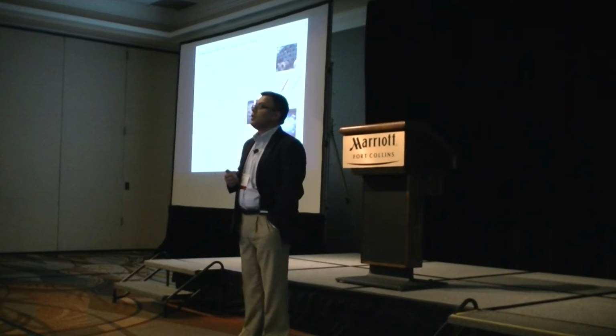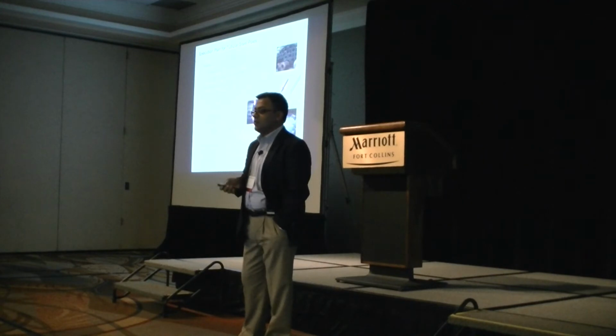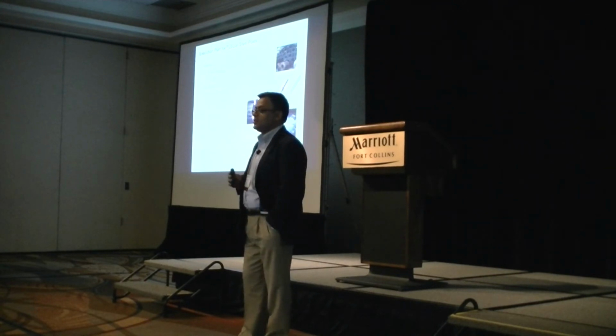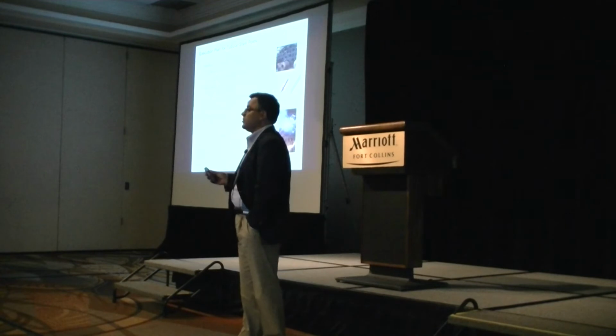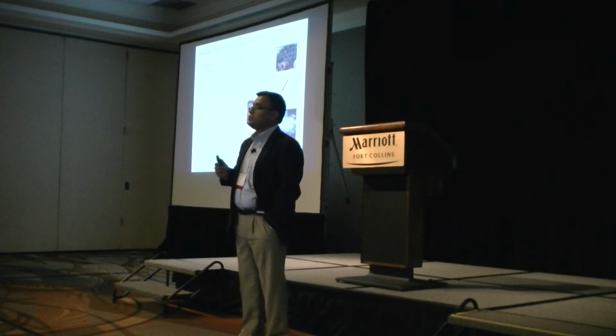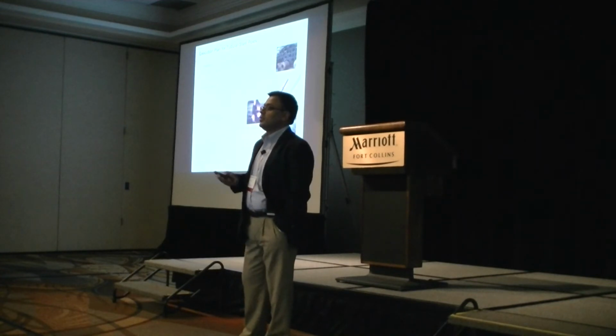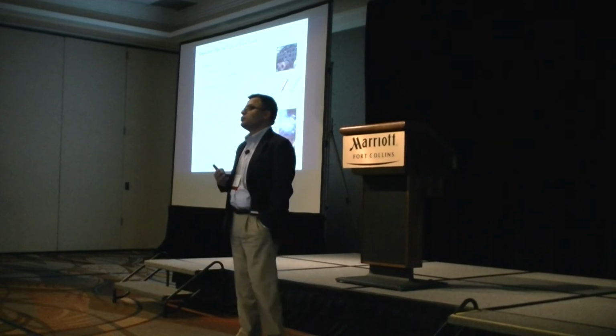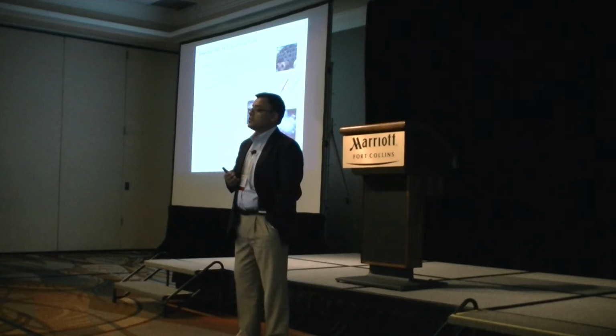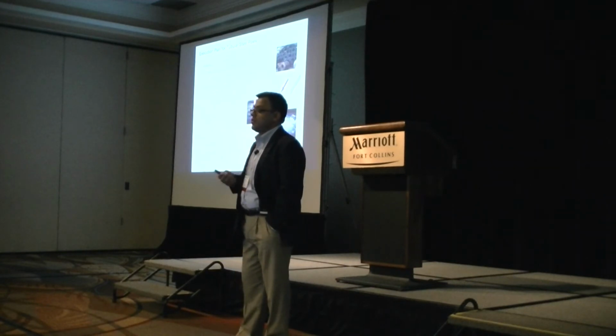First one, the material. As we know, we have the ASTM standard, and we have to make sure that all the steel meets the ASTM requirement. A lot of times the challenge is that if you go international, like China or some other parts, they'll give you a Q spec, which is not exactly like ASTM, but you want to make sure that it has the same characteristics that ASTM requires.